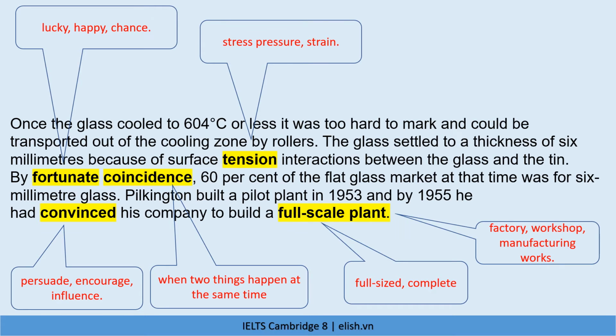The glass settled to a thickness of 6 mm, because of surface tension interactions between the glass and the tin. By fortunate coincidence, 60% of the flat glass market at that time was for 6 mm glass. Pilkington built a pilot plant in 1953, and by 1955 he had convinced his company to build a full-scale plant.